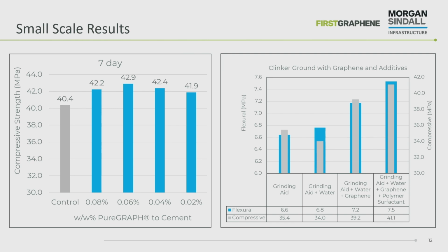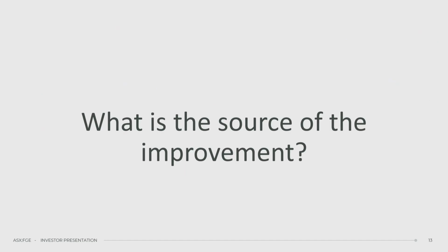So we're just making sure that none of that has a detrimental impact, and we also did some tests with some polymer surfactants, just some PCEs, to see if we could get an even greater improvement. We ended up not using the polymer surfactants in the trial, just the graphene and the grinding aid and the water, and that was able to be pumped in. So why is there an improvement at all?